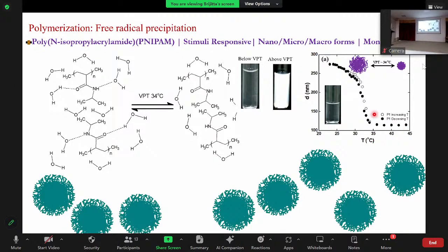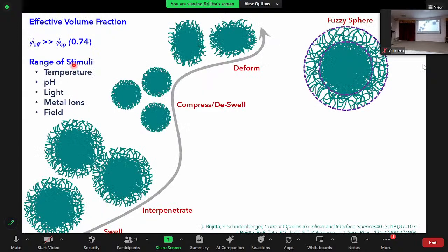So if you calculate the volume fraction, which is given as pi d cube by 6 times the number of particles, the number of particles is fixed. D cube means the diameter cubed, and the diameter is also fixed. So for gold atoms or polystyrene spheres, the volume fraction doesn't change. But in the case of gels, because at every temperature you have a different size, your volume fraction changes, because the diameter in the formula for volume fraction keeps changing. And these particles are responsive to temperature. Initially I showed you that it is changing with temperature. Depending upon the solvent in which they are dispersed, the particles can be swollen, they can shrink, they can also deform. They can even form facets, which I am not showing here.